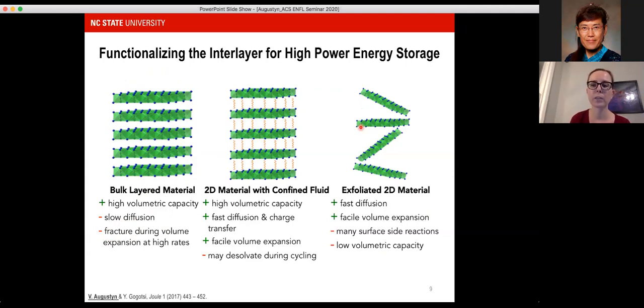two-dimensional materials like graphene. And studies have shown that now, because you have essentially the entire surface that can be exposed at your electrochemical interface, you don't have to worry about transport processes. You're not limited by any solid state diffusion. Any sort of volume expansion that takes place is easy because you have plenty of space.